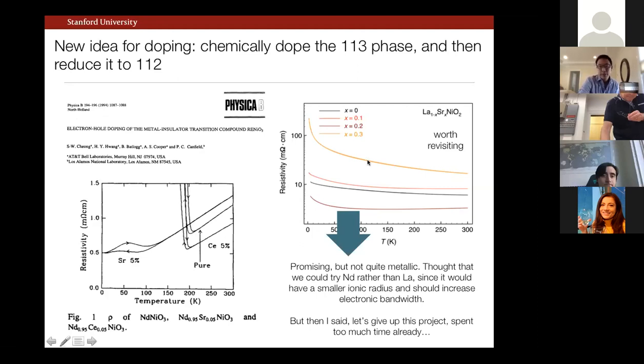tried lots of things, initially in the lanthanum strontium version of the system. And you can see here, I should say this was preliminary work. It's probably worth revisiting, in that we know much more now about the synthesis of the system than we did back then. But what you can see from his resistivity as a function of temperature traces is that it's not so systematic per se, but with doping, and especially with about 20% doping, we have a minimum in resistivity, okay? So this starts to seem interesting. It's on the verge, qualitatively, of looking metallic.